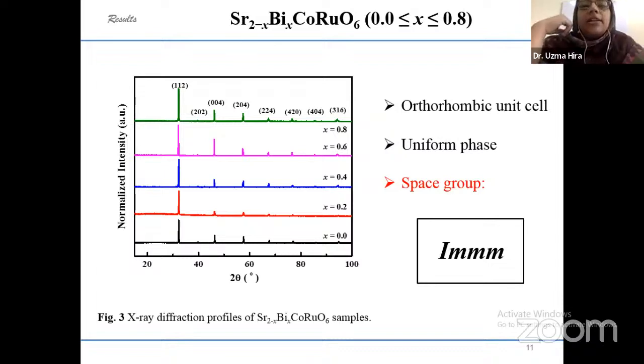I have prepared a series of bismuth-doped strontium cobalt ruthenium double oxide materials. As you can see, these are the XRD patterns for this material at room temperature. All of the peaks could be indexed with an orthorhombic unit cell within the space group Immm symmetry, which indicates that our material is pure and there are no impure phases present. So this material is ready for further analysis.